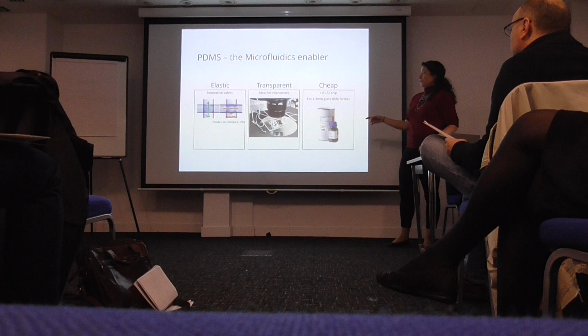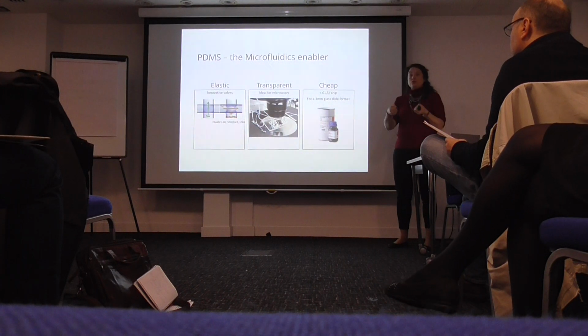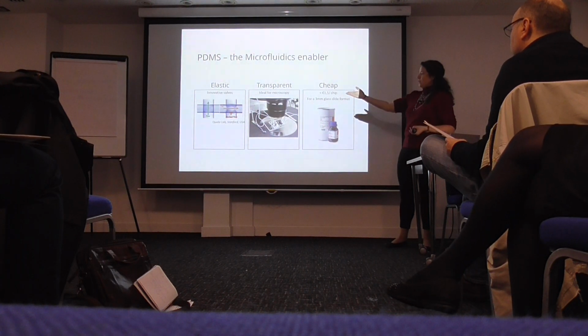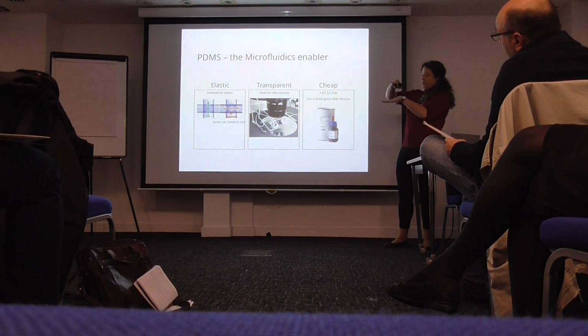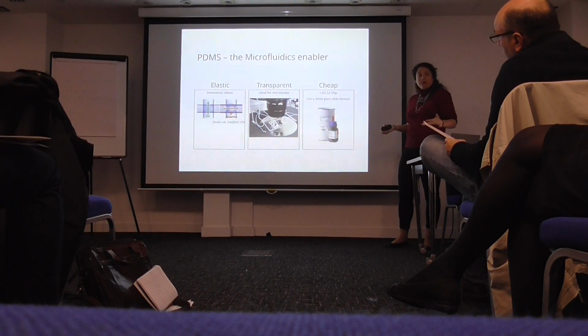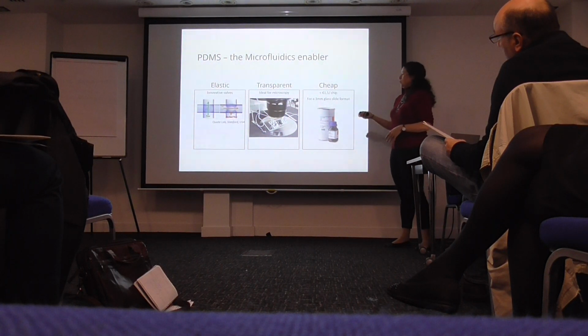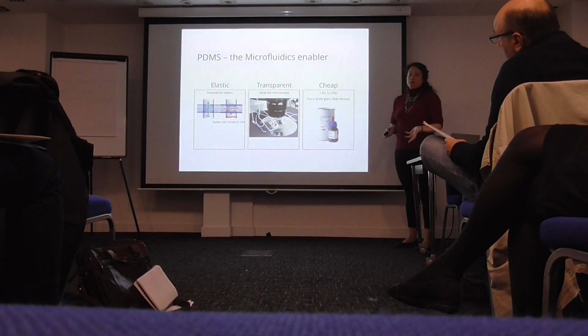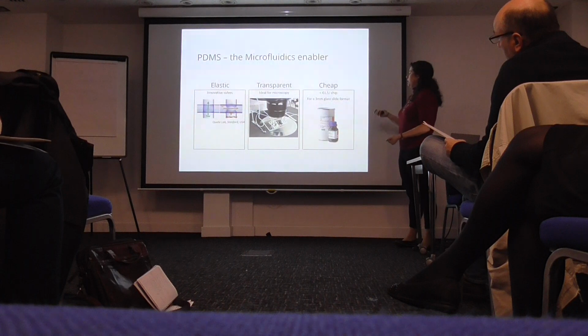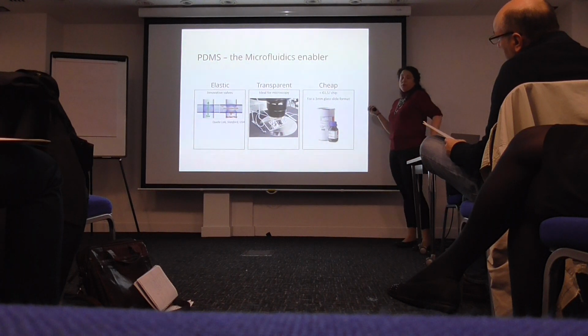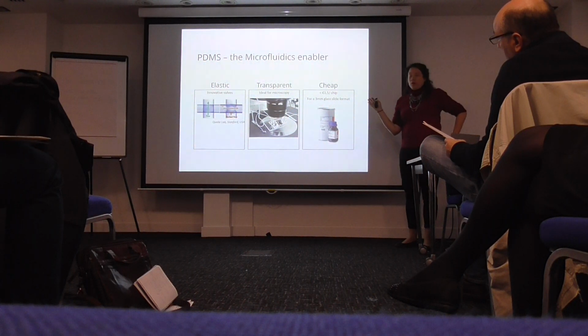It's elastic, which allowed us to do the stretching of the membrane, create valves where you put two channels on top of each other and you inflate this one and it's going to squeeze that one. You've got a very easy mechanical valve. It's transparent. It has very low fluorescence on its own, so you get very low noise, and it's fairly cheap. For a lab, it's fairly cheap.